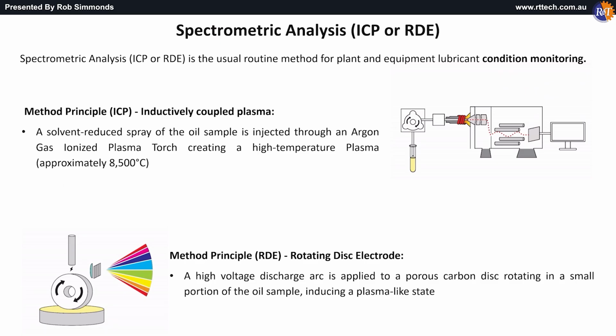Spectrometric analysis, ICP or RDE. Spectrometric analysis is the usual routine method for plant and equipment lubricant condition monitoring. Method principle ICP, inductively coupled plasma: a solvent-reduced spray of the oil sample is injected through an argon gas ionized plasma torch, creating a high-temperature plasma, approximately 8,500 degrees Celsius.